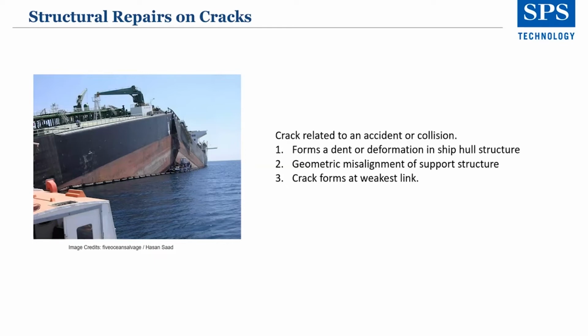Once a crack has been found, a repair procedure, depending on the severity and location of the crack, must be put in place. A newly built ship is expected to be crack-free, and cracks are unlikely to be caused by operational issues such as corrosion or fatigue. Design and construction or conversion related issues are most likely to be in the hull structure during this period. To reduce the possibility of missing cracks, the shipbuilder, class surveyors, ship owner, and operator, through visual inspections and NDE, can hopefully identify any flaws.